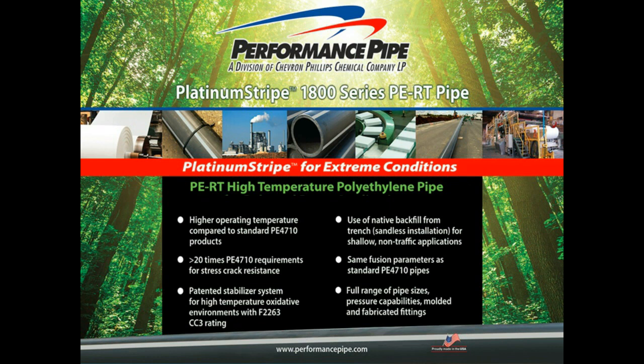We have all the questions, Heath. Well, probably this other one here is another frequent question we get because it's kind of a concept that's a little bit new to North American markets, and it's in regards to a sandless backfill with the product. Essentially, the material has a very, very high resistance to stress cracking. Like in Europe, there's a classification of resins called PE100RC for resistance to cracking, and those are promoted for sandless installations because they have very, very high stress crack resistance, so they're less prone to rock impingement type stress cracks. So the same with this material. It has a very high resistance to stress cracking.